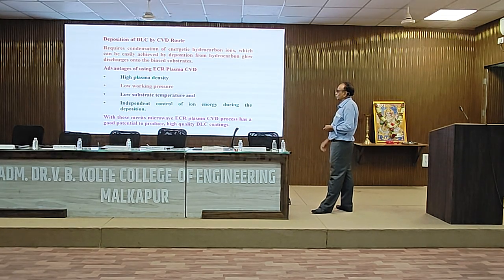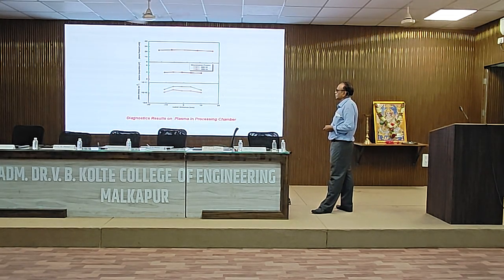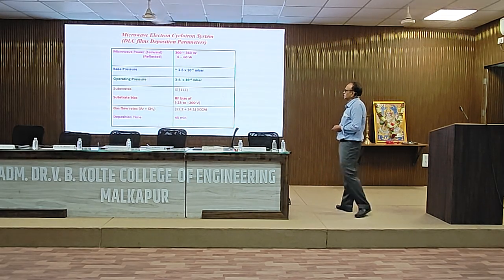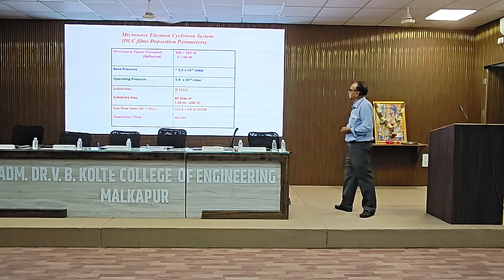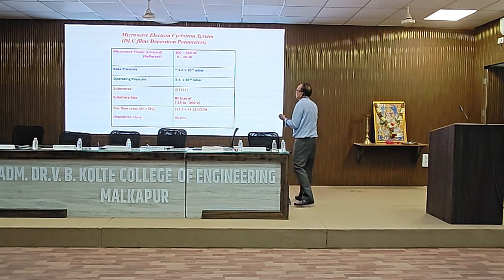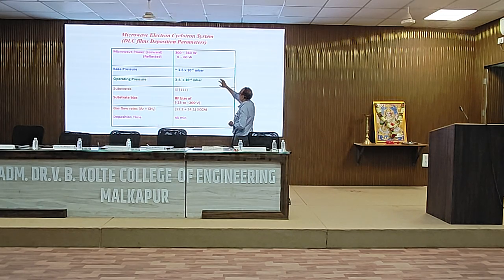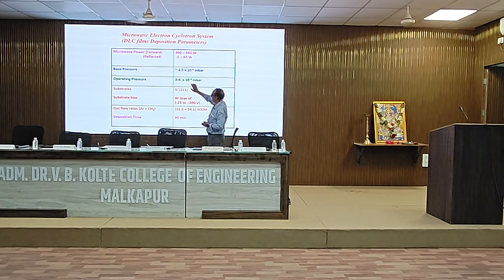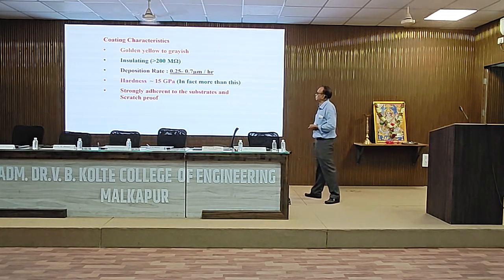Of course, I will not go through this. See, again an 8-inch diameter uniform plasma was obtained. We deposited some diamond-like carbon using this facility. Microwave power used was 400 watt. This was the base pressure. This was the operating pressure. Substrate was silicon 111. It was biased with a negative bias from 25 to 200 volt, and an argon and methane mixture was used, for almost 45 minutes.